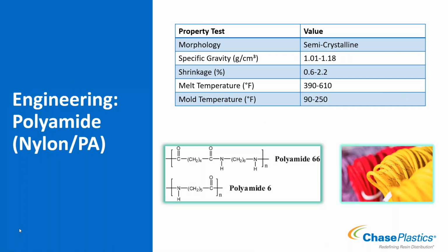Mold temperature and melt temperature again have a big range, because the longer chain ones are processed and run at lower temperatures, more in the 390-400 range, all the way up to your high temperature ones like a 4,6 that are going to be more in the 500-600 degree range. So a big range here. I included the chemistry for two common ones we're most familiar with, polyamide 6,6 and 6, but I also included 4,6, and 12 within those ranges as well.